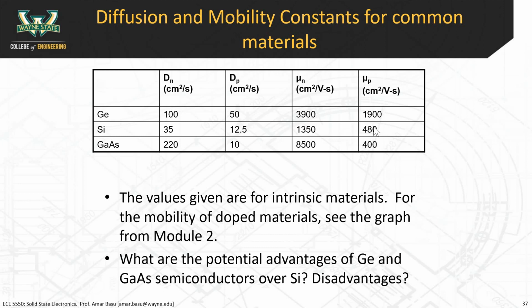The second thing that we talked about was impurity scattering. That's the one, David, you were thinking of. Impurity scattering is determined by the dopant ions, right? So what happens if we increase doping? Mobility decreases. Right, if you dope the material more heavily, you get more impurity scattering, and therefore that would reduce your mobility. So these mobility numbers given in this chart are only for room temperature at low doping concentrations. In an actual exam, you would get the doping versus mobility chart for silicon.